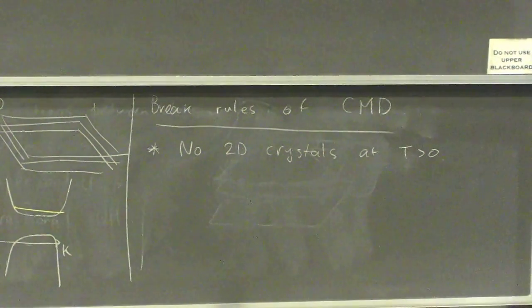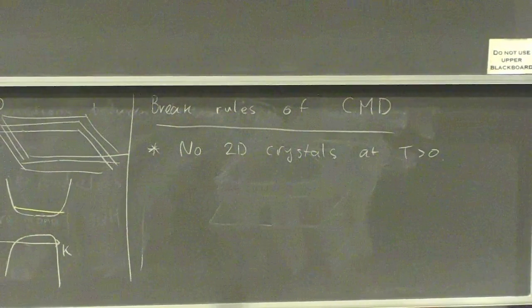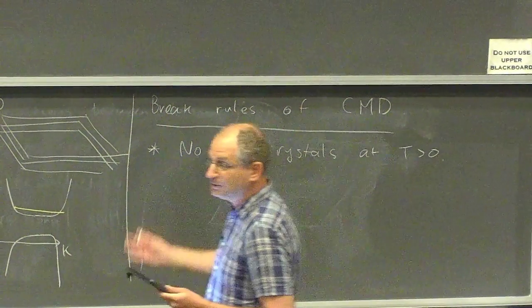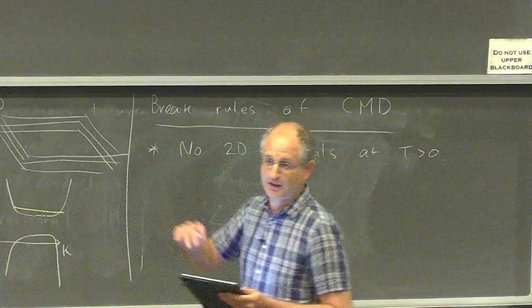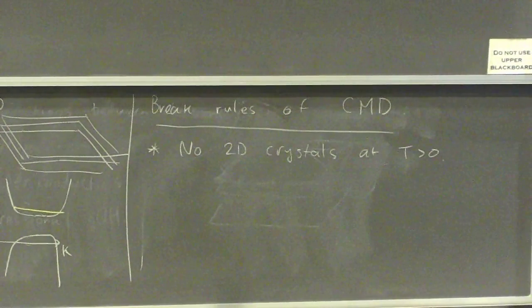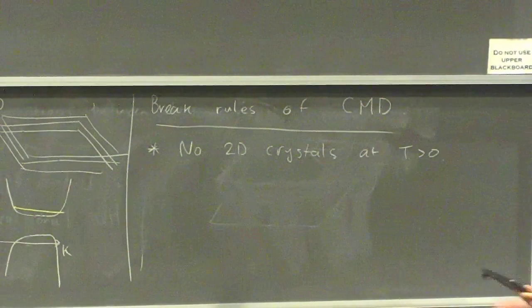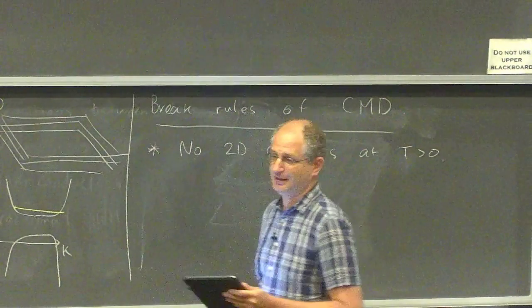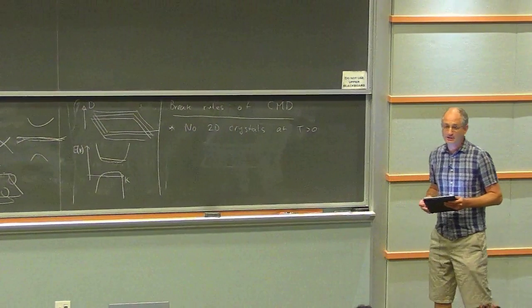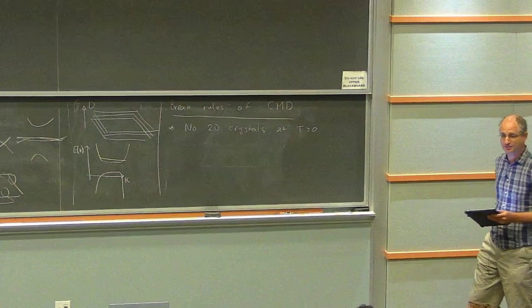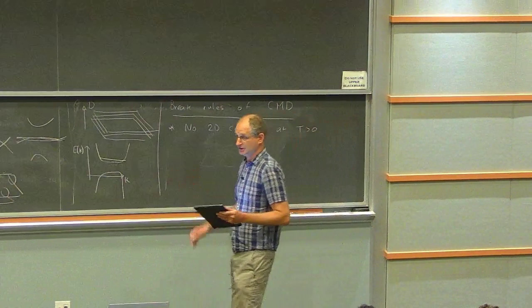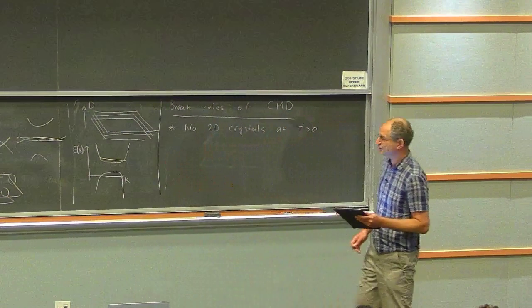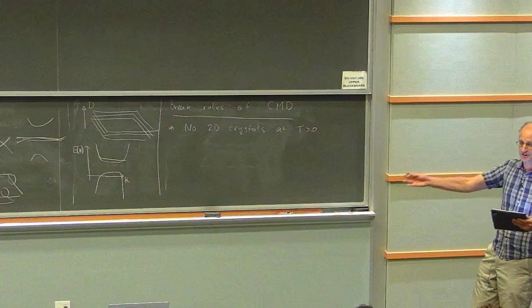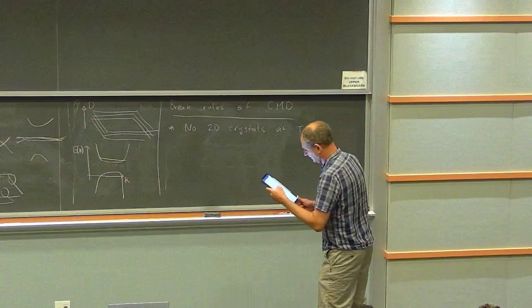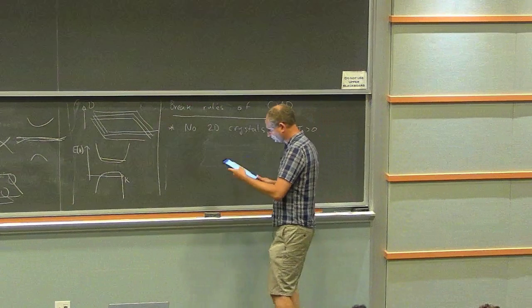Very well-known result from statistical physics: we can't break a continuous symmetry in 2 dimensions. Thermal fluctuations would always destroy long-range order. So how do we even talk about 2D materials at finite temperature? And yet, here they are. Ultimately the reason they exist is that we're always talking about finite systems, and the system is just not big enough to see the effects of these fluctuations. These crystals are rigid enough such that over our length scales, this doesn't show up.